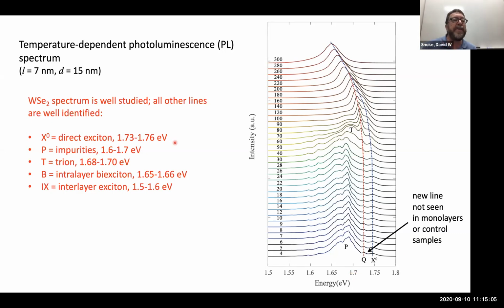So what do we see? In our various samples, we've got the exciton well-established, impurities well-established, trions well-established. The biexciton is a strong function of pump power because you have to have 2 excitons finding each other. And so the biexciton only appears at high pump power. And the interlayer exciton appears way down here. And this little bump might actually be a vestige of that.